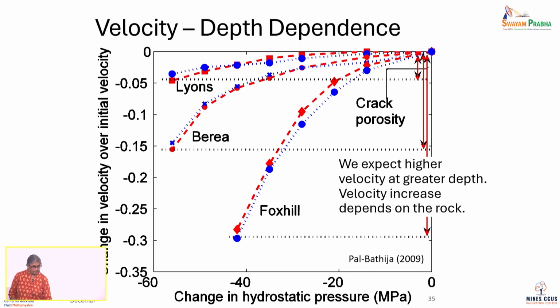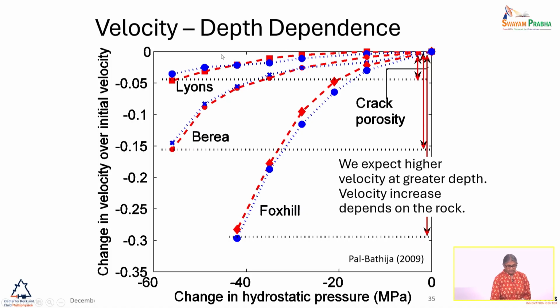We can also go in and look at change in velocity over initial velocity. This information is coming in from lab data at no pressure. This is where we are at benchtop. And then as we start increasing pressure, we start getting these. There are some that have really very high change in velocity, about 30% change in velocity over the initial velocity. In this case, only about 5% change. And so we see that depending on what sort of material we have, cracks over here, and we have very stiff pores in this case. So we see a difference in change in velocity as a function of stress.